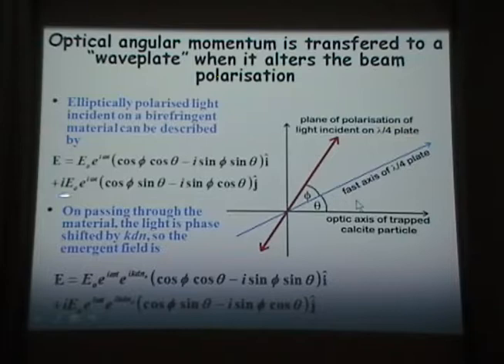Okay, so I can write my electric field vector, and this is the expression for it. Now the light is passing through the material, and the light is phase shifted by k dn, where dn is the change in the refractive index and d is the thickness of the birefringent crystal, and the emerging field will be given by this expression here. Then for a plane wave, the total angular momentum of the field is given by this expression. So the angular momentum densities of the field before, L0, and after, L final, passing through the crystal are given by these two expressions. This is the original one, and then the light goes through the birefringent crystal.